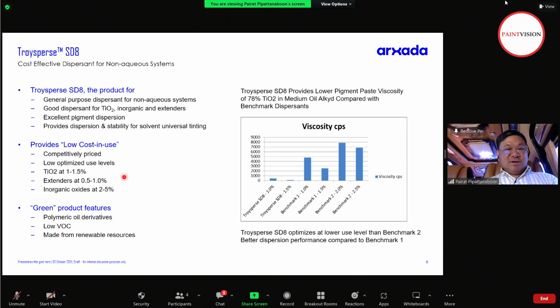Similar to SD8, for TiO2 use about 1 to 2% in your formulation based on the pigment weight, and for inorganic pigment like oxide pigment, you use about 2 to 5%. The study here, we tested in a medium oil alkyd with 78% TiO2, quite a high pigment loading, and either 1% of SD8 or 1.5% of SD8 on the pigment weight. You compare with benchmark 1 at similar doses, or benchmark 2, which is higher,